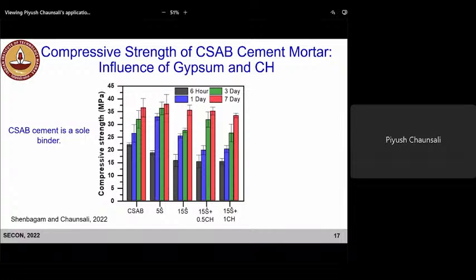One of the advantages of this cement is you are able to get very high early age strength. In 6 hours, this CSAB cement is able to attain 20 to 25 MPa strength. Again, this is mortar strength, and you can see here how it evolves with time. So this is just CSAB cement mortar, right? And what you see here is the effect of gypsum addition. Let's say if we add 5% gypsum, right? Because this non-expansive cement can also be converted to expansive cement.